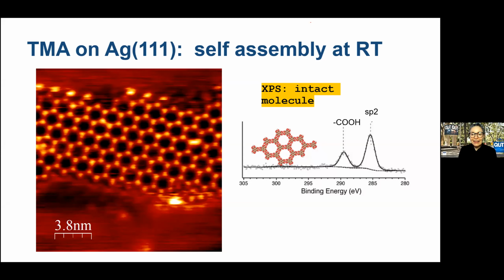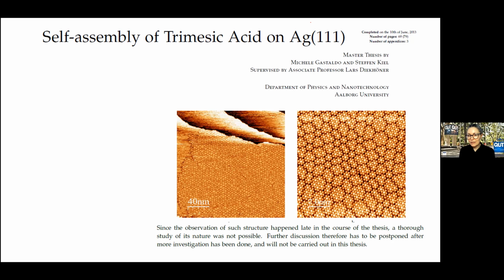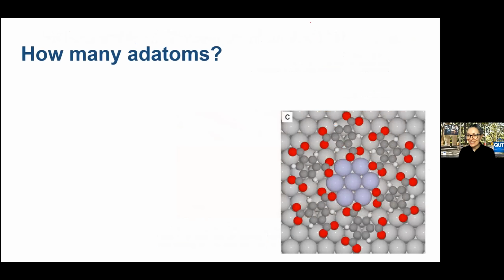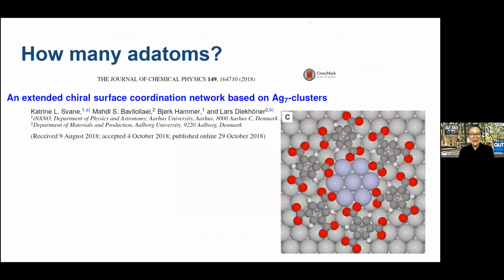So we were able to provide some insight based on the fact that our microscopy was combined with the XPS, which allowed us to comment on the chemical state of the molecule and to better understand what was going on. Actually, immediately after we published it, we realized that they were still working on it in Denmark, because very quickly after our publication came out, this really nice theoretical paper demonstrated that the center bright protrusion in this network actually comprises 7 silver adatoms. 6 of them bear the same oxidation state, and the one at the center is slightly different. It's a really fascinating set of results reported in this paper.